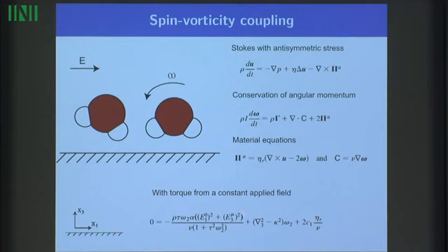This E3 mu is the field coming from the orientation of the water molecules, and it all depends linearly on omega. So it means that there is one solution for omega equals 0, which is the solution of minimal entropy production, so that's the stable solution that we have, and it depends quadratically on the electric field, so that means that you will never be able to actually induce any torque. There are two arguments that you can see immediately that this will never work. You will never be able to get any non-zero mobility out of a pure dipolar fluid.